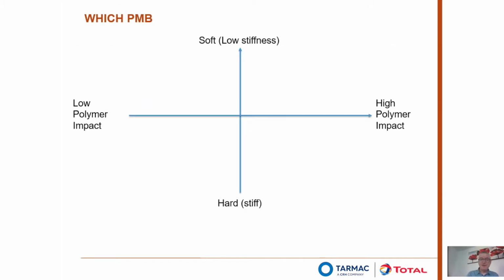Now I want to focus very much on polymer modified bitumens because I see there's going to be an increasing use of them, because of the real benefits they can offer in terms of resistance to road stresses and the contribution they can make towards durability of the asphalt surface. We can look at the impact in terms of how stiff the polymer modified bitumens are, whether they're very hard bitumens, i.e., very stiff, or very soft bitumens, i.e., low stiffness, but also in terms of the polymer impact, whether it's low polymer impact or high polymer impact.